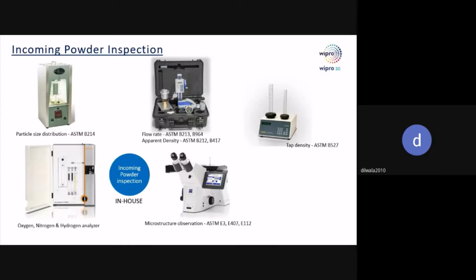So these are the different tests that we do. PSD or particle size distribution. In this, we check how the powder is distributed. As we know, if we ask for 63 micron powder, every particle may not be 63 micron. It may fall anywhere between 45 to 75 microns. The distribution is calculated by sieving the powder, weighing them, and deriving the proportion from those particle sizes.